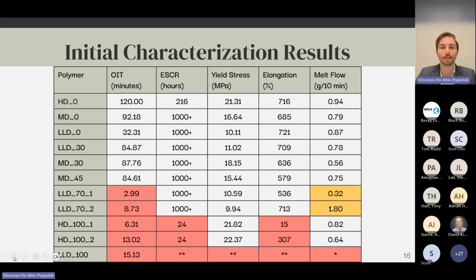However, of note, the HD-100-1 failed at only 15%, having quite a brittle failure, and this was not something that we thought that we could compensate for in blending, and as such was not considered for use. While the HD-100-2 reached 307% elongation, which was much closer to the 400% threshold, and we were hopeful that by blending with a higher ductility polymer, we would be able to surpass that level.